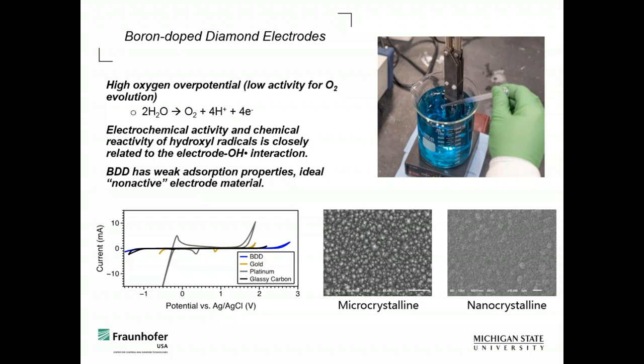But the reason we don't use nanocrystalline diamond for this is that each time a diamond crystal grain meets another diamond crystal grain, that's where sp2 hybridized carbon hides. And we want sp3 hybridized carbon, because sp2 hybridized carbon is glassy carbon. We need the advantages of diamond. So if we have nanocrystalline diamond, we have a significant amount more crystallites, therefore more grain boundaries, more sp2. So when we push this voltage current up, we just etch the sp2 to carbon dioxide for the same reasons that we can oxidize an organic contaminant. So I won't really go into the doping procedure and all that, but we gear our processes towards high sp3 content.